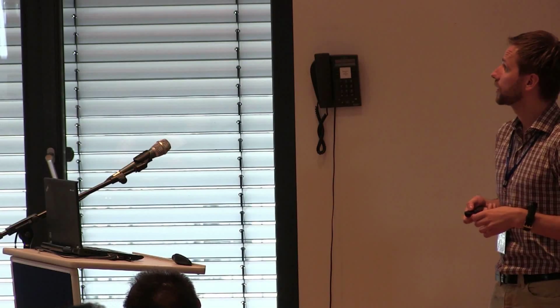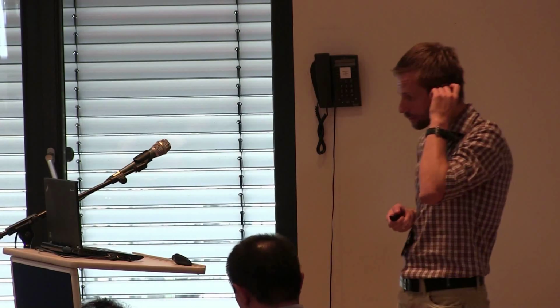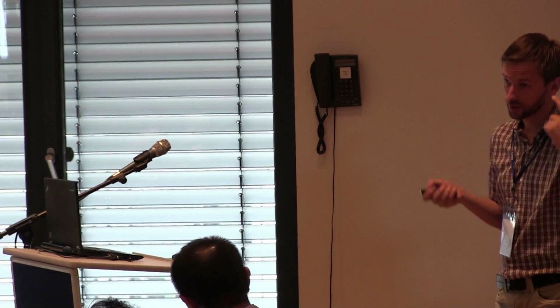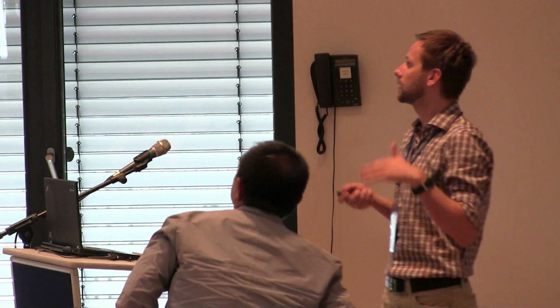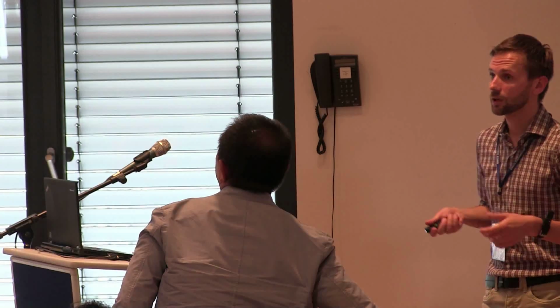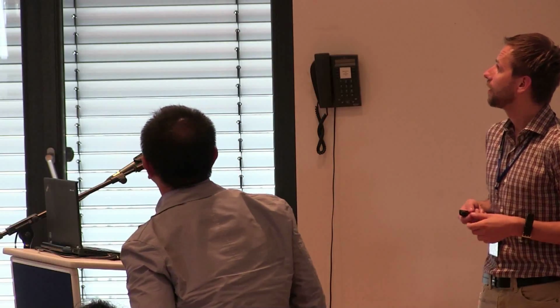And that brings me to the conclusions. I hope I could convince you that the Terahertz conductivity of graphene is simply defined by the thermodynamic balance maintained within its electron gas and nothing else. And then the high electron temperatures lead to reduction of the chemical potential and therefore to reduction of intraband Terahertz conductivity of graphene. Thank you very much.